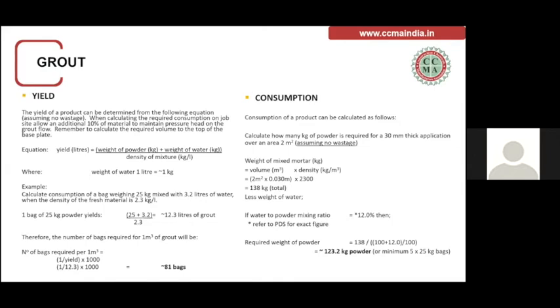Calculations of this grout: when we start, we know that this much volume is there, like 0.5 cubic meter or 1 cubic meter volume has to be filled. So we need to calculate how much grout material is required, so that, as I said initially, the grout pouring should be uninterrupted. There should not be any kind of break in between the pouring. So that much volume of grout material should be kept ready. Pre-batching should be done. The amount of water should be pre-batched, and then the grout mixing should be done. So here you can see the yield calculation, a very simple calculation: the weight of powder plus the amount of water which is being added to this.